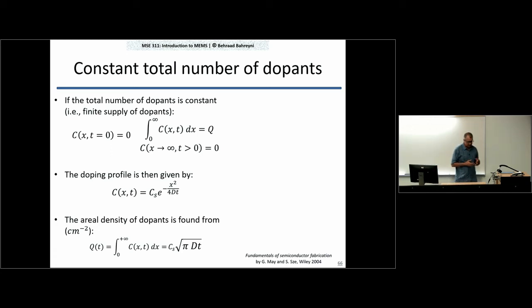So in this case, I have a new set of boundary conditions and initial condition. The initial condition is the same. The concentration at infinity goes to 0, so this is the same as before. But the other boundary condition is that if you count the number of dopants as they go into the silicon, it is constant. You're not bringing in new ones. So that's a fixed number. Whatever you put in at the beginning, when you integrate C of x and t over the entire depth, it should remain constant. You're not bringing new ones.